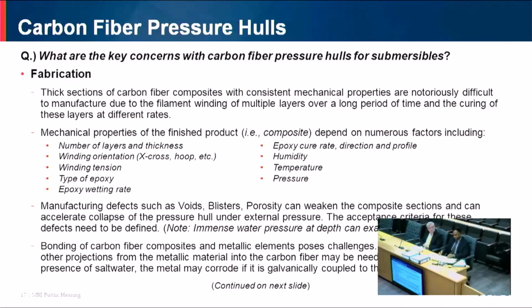Another important consideration is the winding orientation. Now, a typical thick shell pressure hull is exposed to hoop stresses, radial stresses, as well as longitudinal stresses. Okay. Now, if your winding is hoop winding, that means if you wind the carbon fiber composites around the cylinder in a hoop fashion, that is only good for withstanding hoop stresses. It cannot withstand radial or longitudinal stresses. So to withstand radial or longitudinal stresses, you typically employ X cross winding. That means you wind it in an X pattern, okay? And that is more effective in handling hoop as well as radial as well as longitudinal stresses.